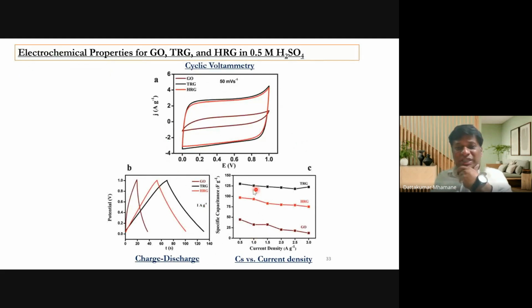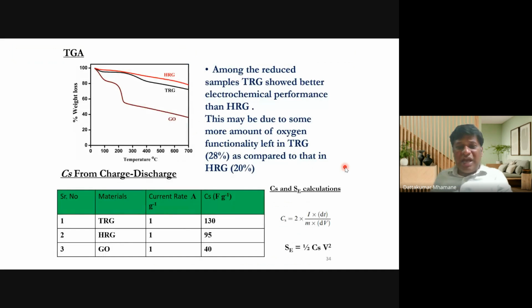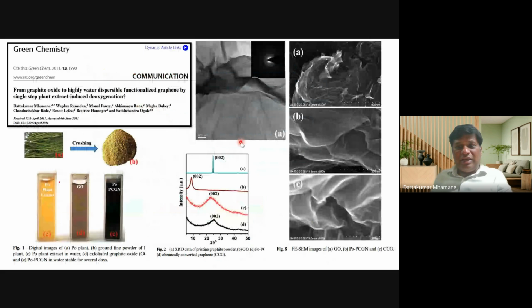And this is charge storage. You can see trigol based graphene delivered 125 farad per gram specific capacitance, compared to hydrazine reduced graphene, and this GO is not showing any capacitance at all. These are the charge storage performance or electrochemical properties. I'm not going into the details. What I want to highlight is that our trigol reduced graphene at 1 ampere per gram applied current, where the material loading is 1 milligram per centimeter square, delivered a specific capacitance of 130 farad per gram, whereas hydrazine reduced graphene delivered only 95.